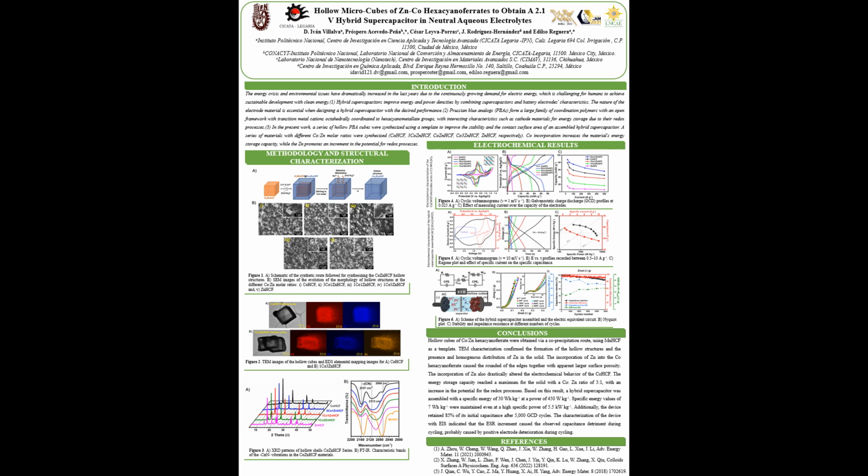R sol represents the solution resistance between the two electrodes, and the storage capacity, C store in this case, of the whole device is expressed as a contribution of the carbon and the Faraday electrodes. Figure 6b shows the experimental Nyquist plot for the hybrid supercapacitor at a fully charged state and after several galvanostatic charge and discharge cycles. The plot shows the typical behavior expected for a supercapacitor.